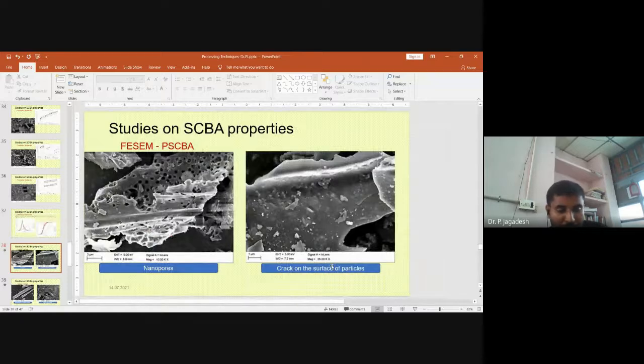Then I had done morphological studies again to see how the structure is improved. Earlier you can see macro size pores in original sugarcane bagasse, whereas in processed SCBA you can see these pore sizes are in nano size. Then you can see cracks on the surface texture or surface morphology of the particle.